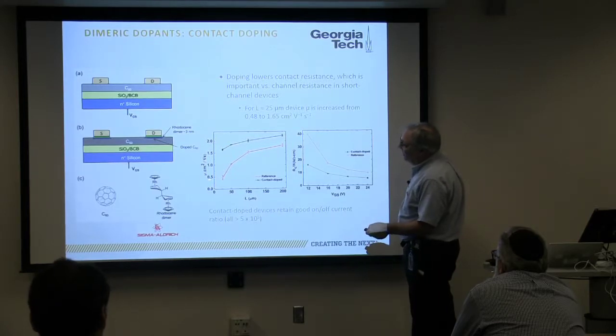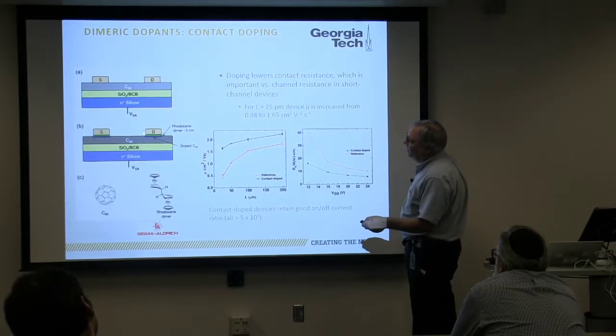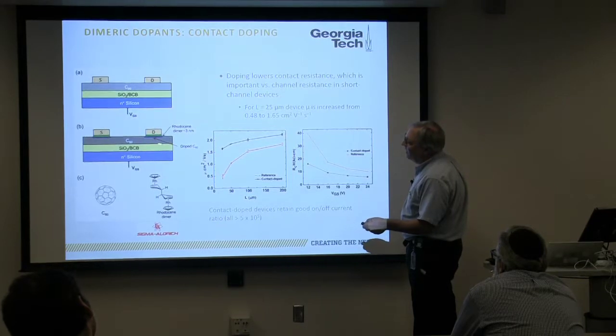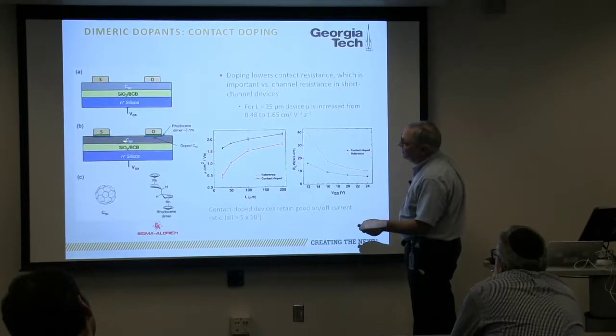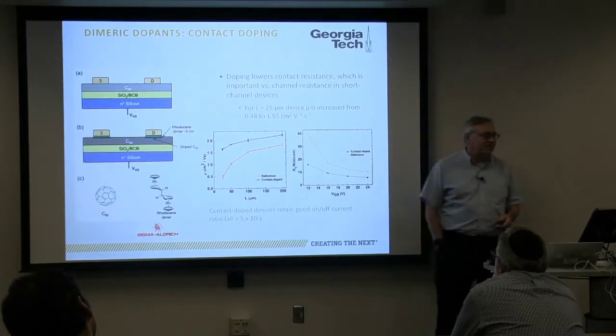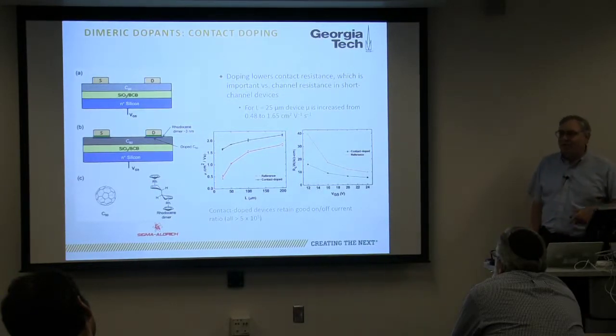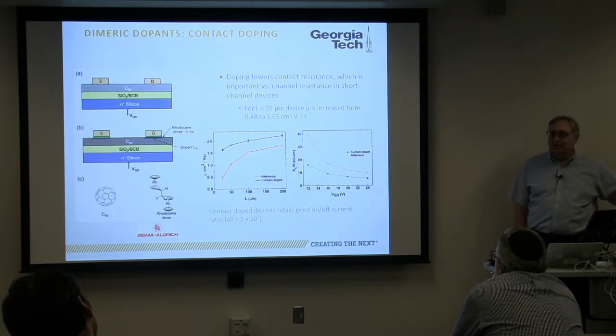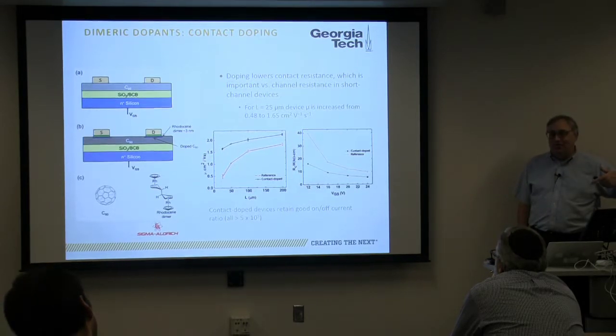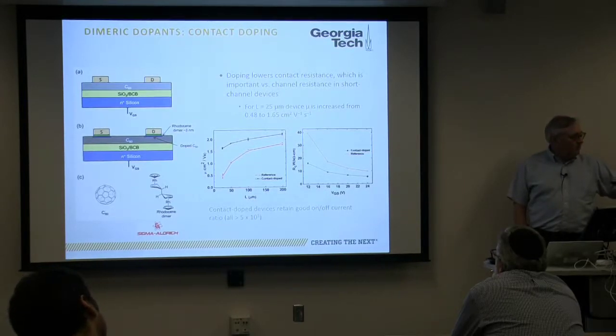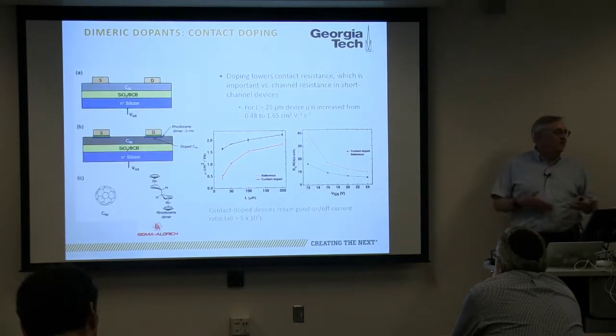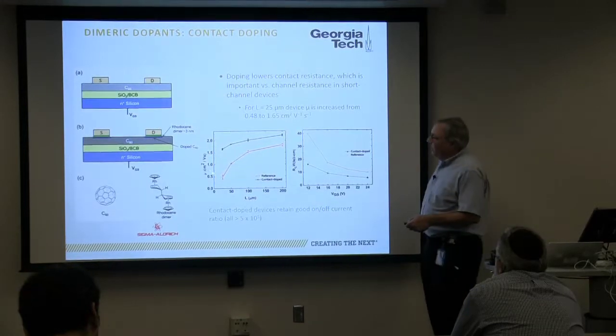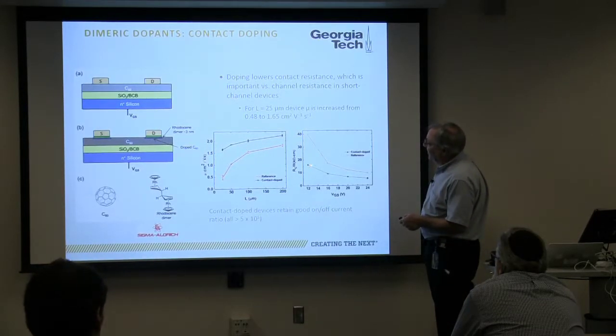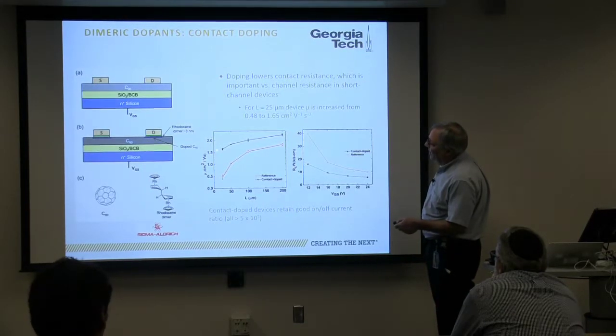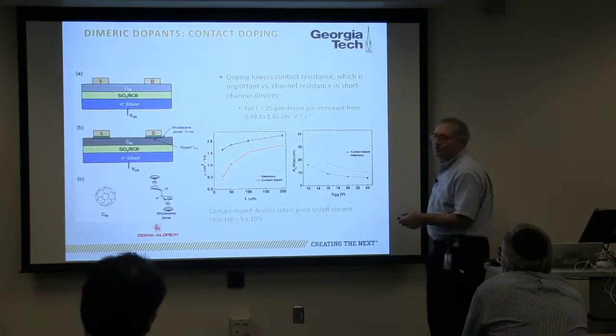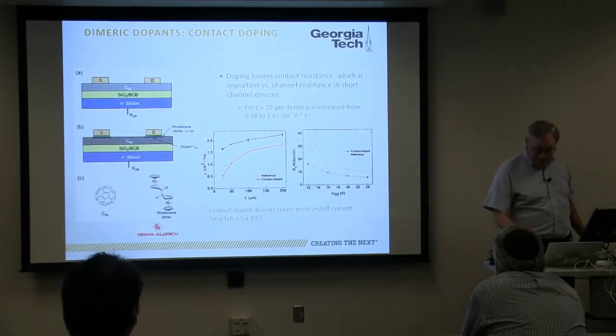Okay? Why is that? Because here the current was not limited only by the resistance of the C60, but it was limited by the contact resistance at the electrode. And for many of you who might be thinking about working with graphene and other 2D materials, I have been told by the people who have worked on them that dealing with the issue of contact resistance is one of the challenges that you have to make good materials. So here, what happens is the contact resistance goes down by a factor of 2.5, okay? And therefore, the measured mobility gets closer to something that is representative of the intrinsic mobility.